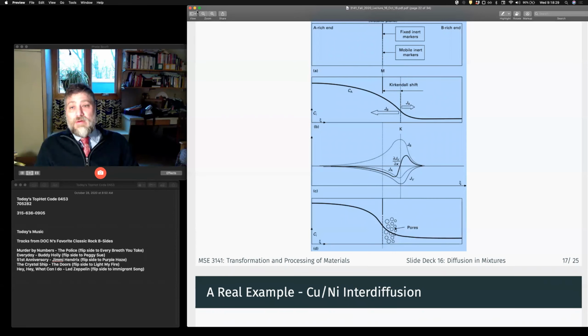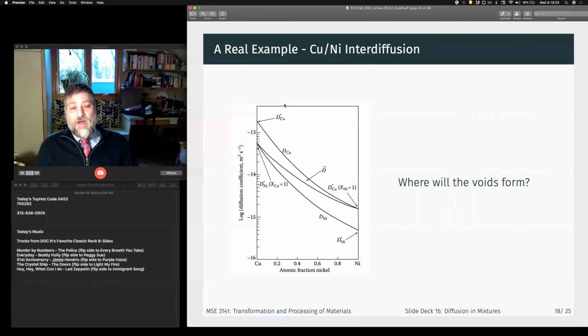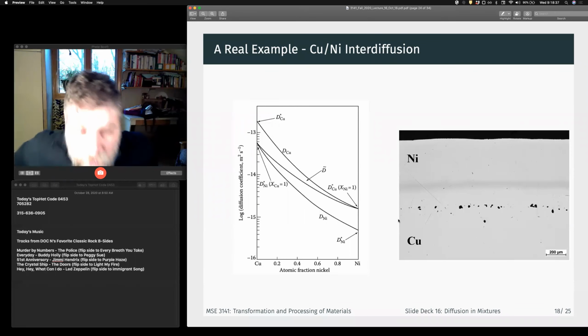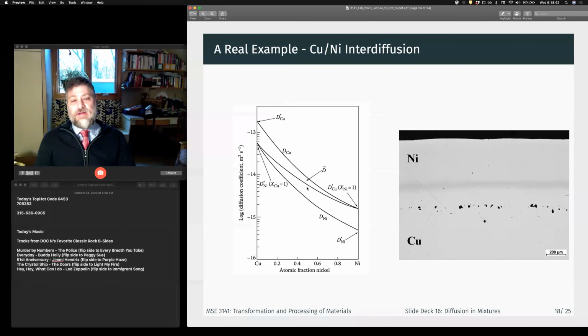Where I went a little fast is when we were talking about this. I said, where will the voids form? And I pointed out the interdiffusivity, and I think I may have given some people the wrong idea, right? The important thing to look at is the relative diffusivities. The self-diffusivity of copper in copper is much higher than the diffusivity of nickel in copper, right? And the diffusivity of copper in nickel is higher than the diffusivity of nickel in nickel, right? So at any concentration, the diffusivity of the copper is faster than the diffusivity of the nickel,